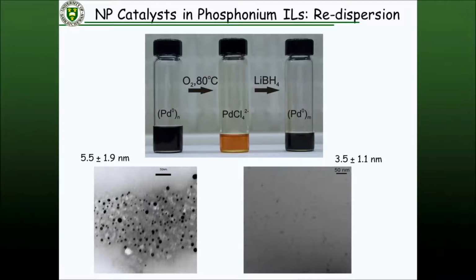And so this idea that we've got a system now that we can potentially keep reusing over and over again, and then anytime the activity starts to die on us, we've got a possible, very simple, one-pot route that essentially involves oxidizing in air and re-reducing to form smaller particles. So that was the system for palladium.